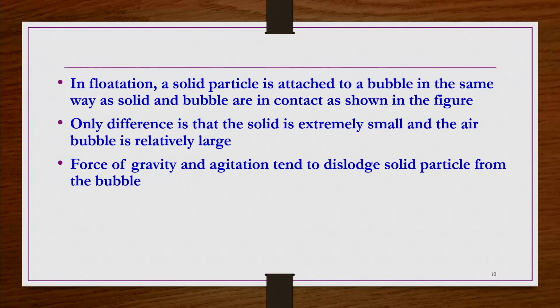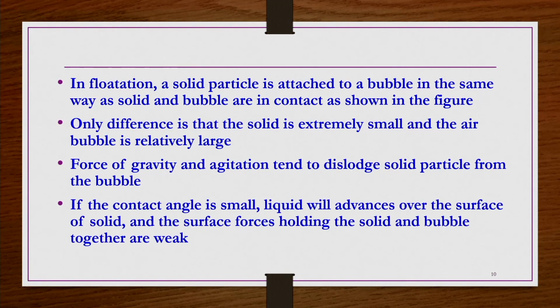Force of gravity and agitation tend to dislodge the solid particle from the bubble. If the contact angle is small, liquid will advance over the surface of the solid and the surface forces holding the solid and bubble together are weaker. As I said, if the contact between the gas bubble and the solid is not there, then obviously the separation will not take place in the flotation. So, that means the smaller the contact angle, the weaker is the interaction between the solid and the bubble. Okay. So, then the performance of flotation would be weaker.